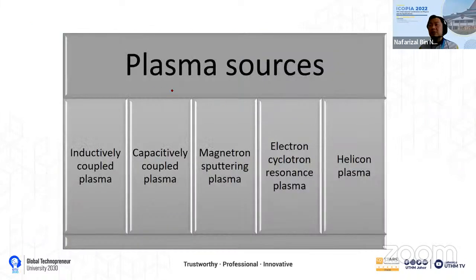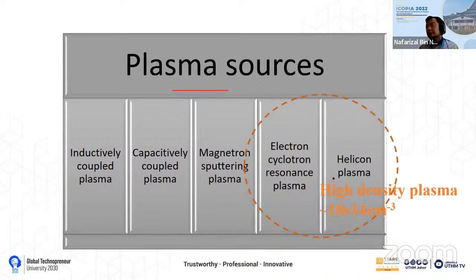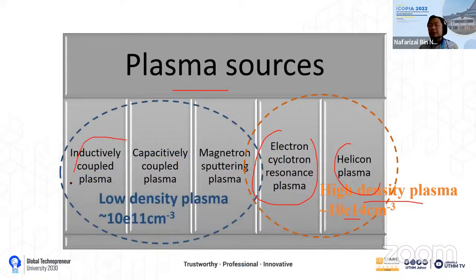So these are some of the plasma sources that are available in the market. Starting from the right are the helicon plasma and the electron cyclotron plasma. This is the type we call high density plasma, where the density of the ion inside this plasma is up to 10 to the power of 14 per cubic centimeter. It's quite rare, this kind of device, but for the sun to produce high energy, we need this kind of high density plasma. On the left is the so-called low density plasma, where the density is like 10 to the power of 11.